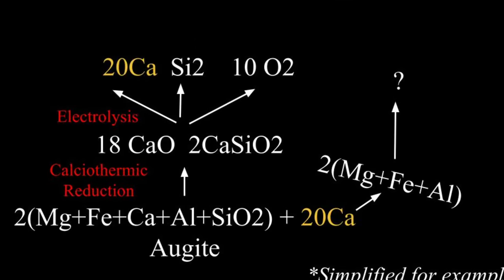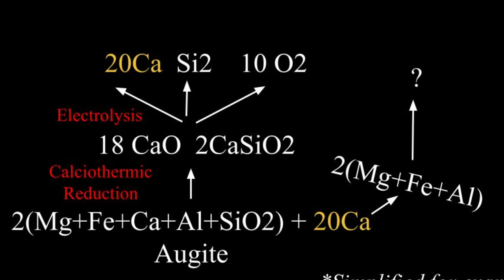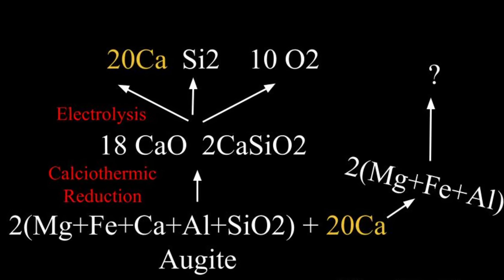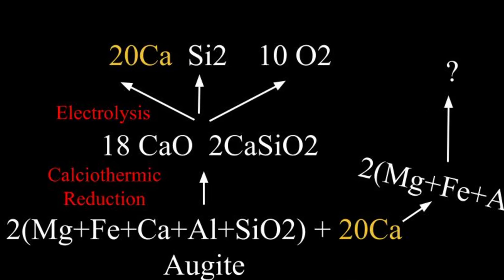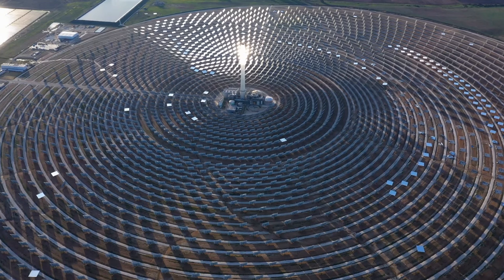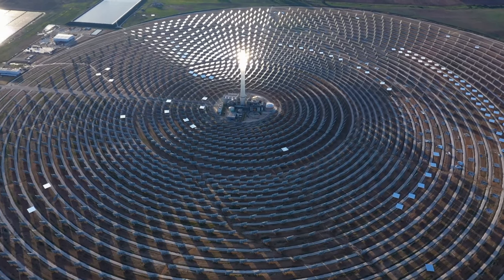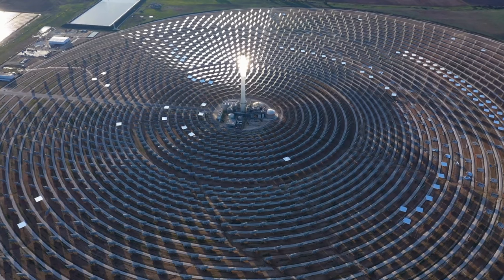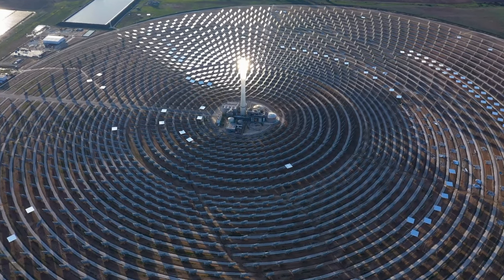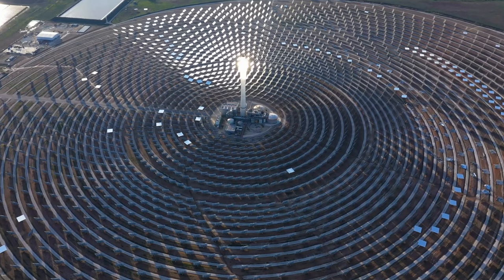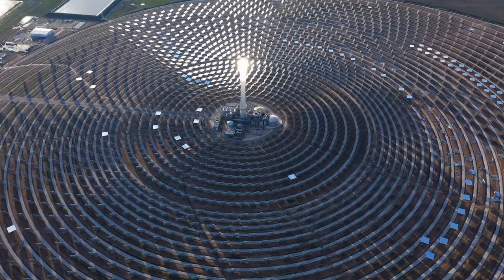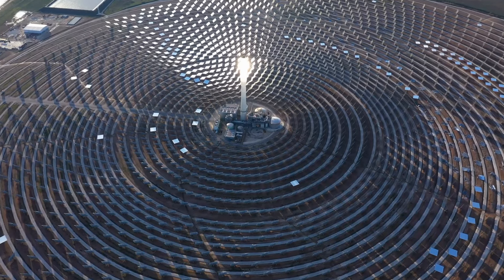Now at this point, even with our solar calcium furnace, it's important to note we are still using electrolysis to process the calcium silicate and calcium oxide into calcium metal and pure silicon. And this step is still the largest energy consumer in the entire process. Our current calcium blast furnace method is not a standalone thing. Rather, it is an efficiency-maximizing step of the electrolysis process, just with less direct regolith raw dogging and more careful preparation. And while this approach is less hot in general, it saves us a lot of energy and headache in the long run. And so it is the best way of employing the best method of processing regolith.